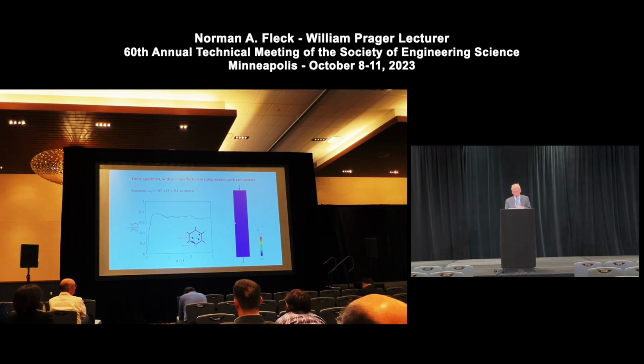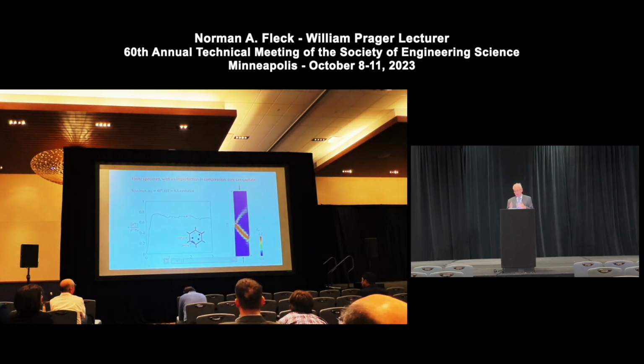So when we allow the cavitation to take place, put a little imperfection into the lattice to try and trigger whatever soft modes it wants to form. What you see are, you can call them, shear bands where there is a slight softening which takes place. It's not huge, it's just a small amount of softening. And although you can say that this is a localization problem and so on, the degree of softening is small and quickly lockup takes place, so it's not very far away from an elastic, perfectly plastic solid.